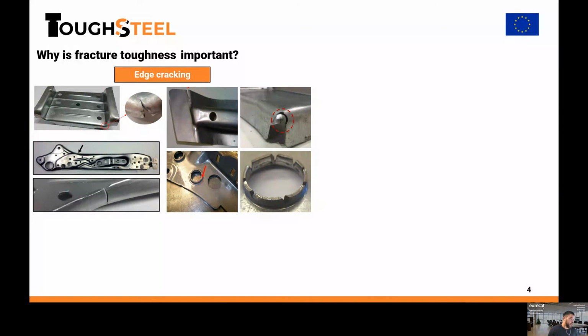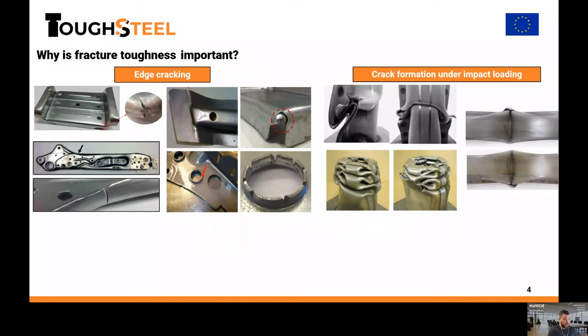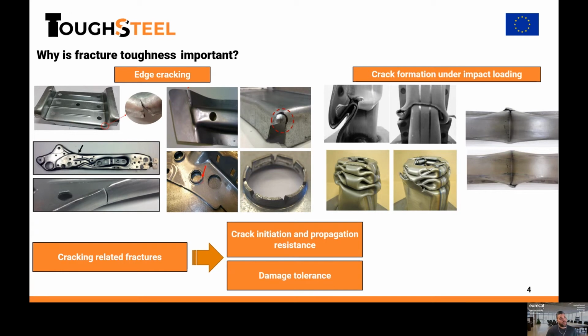These problems include edge cracking during cold forming, in damaged areas, in punctured areas, in trimmed edges, and so on, or also the formation of cracks during impact loading, where the material is subjected to severe plastic deformation. These kinds of fractures, which are related to crack initiation and propagation resistance, to the cracking resistance of the material, and at the end to its damage tolerance, should be addressed through the material property that governs this initiation, propagation resistance, and damage tolerance of the material, which is the fracture toughness.